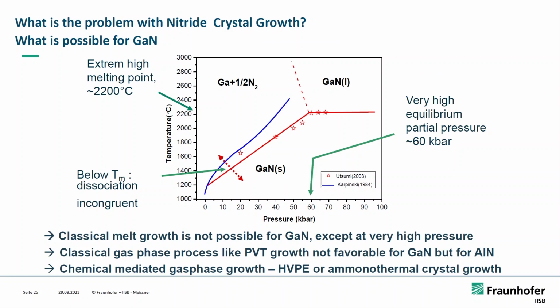The problem is why you cannot melt it and why you cannot so easily evaporate it is shown in this diagram, a temperature versus pressure diagram. You see that gallium nitride is dissociating very fast, and it's neither a congruent melt nor congruent evaporation. You end up with very high equilibrium pressures, so you could only melt and grow it classically under extreme high pressure, which is impractical. This was shown by the community in Poland, but this is very difficult.